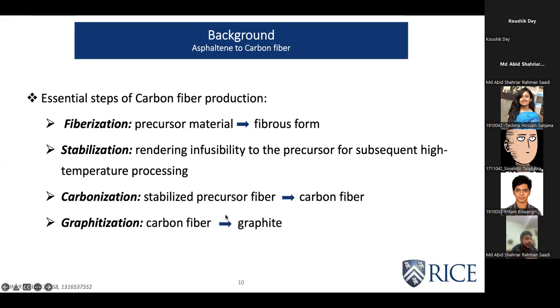And the last step is the graphitization step, which happens around 2000 degrees Celsius or even more. During the carbonization step, carbon content significantly increases to around 85 to 90%. And during graphitization, the carbon content increases even higher and goes to around 99%.